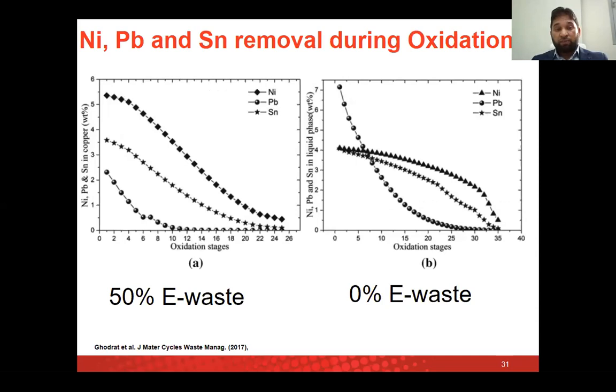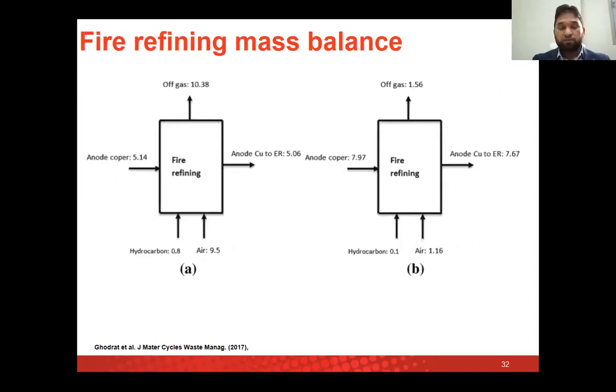Similarly, during the oxidation step, you can also predict the removal of tin, lead, and nickel, these impurities. You can see how the concentration of these impurities is decreasing. Nickel is a benign type of element that does not readily make nickel oxides when it's present with tin, silver and copper. The first element to go is lead, the second one is tin, and then the nickel. Nickel and tin are a challenge again in the copper smelting route, because they remain at the end of the process as well.